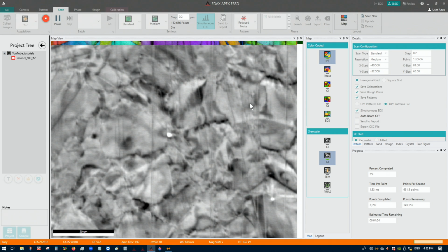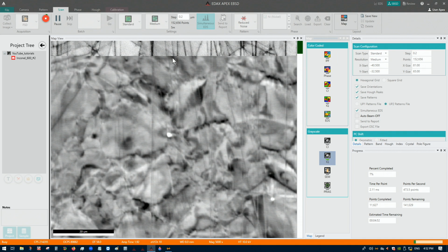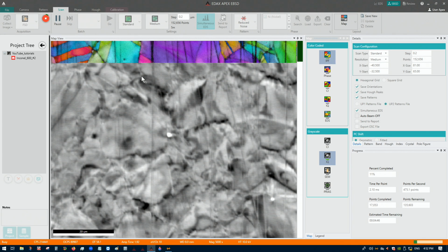So we are seeing right now an IPF, or inverse pole figure map, superimposed on an image quality or pattern quality map. They use this term called image quality to refer to the quality of the patterns. So lighter means higher quality. You can see I have some lovely scratches here, and you can also see where there are grain boundaries as well. That's where we also have lesser pattern quality because two different grains are contributing to the pattern.